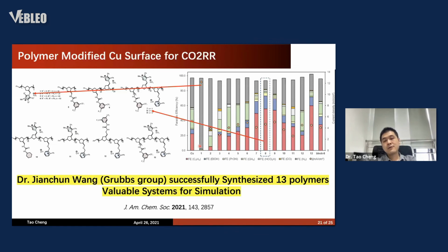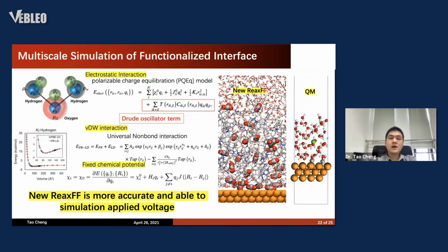We can see that for case number 1, you almost have no CO2 reduction. There is only 2. But if you go to case 8, you can have more than 80% of C2 product. That means that the polymer really plays an important role here. What we are trying to understand is what happens when you have this polymer on the metal surface. In this case, the periodic cell itself is not enough because it's too small. We need to develop some new technique.